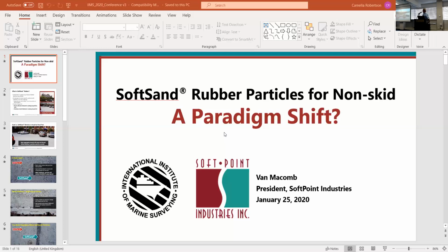This was an exhibit at the Workboat Show the past couple of years, in Savannah, Georgia. This was my backdrop, and it was a nice testimonial. This company, Merrick Marine, started using the rubber particles. We had zero slippage problems since we started using Soft Sand rubber particles on our decks. They're in the process of converting all the barges and boats over to Soft Sand from Black Beauty. These spuds are used to anchor the barge. He said he picked the 10-ton spud off the deck, and there's no crushing of the aggregate, so he couldn't tell where it had been. So it's a nice little testimonial that I use for the Workboat Show.